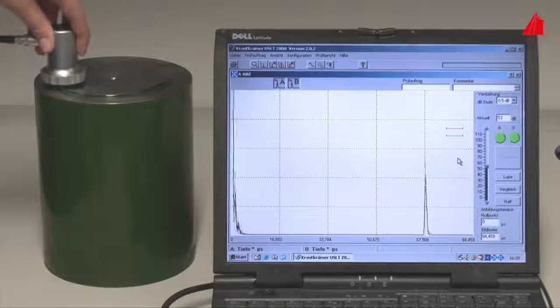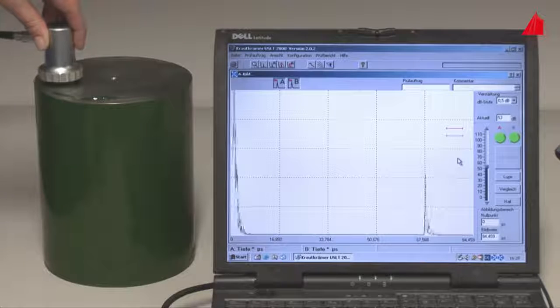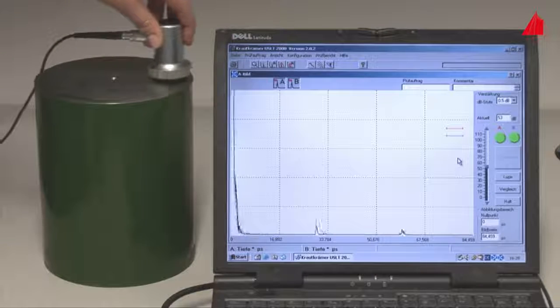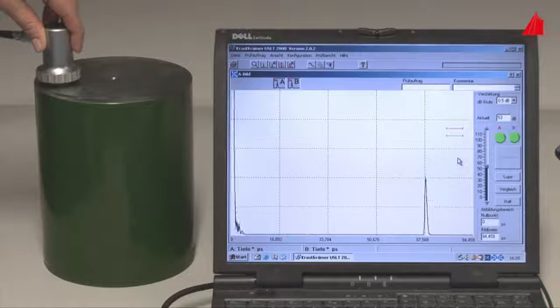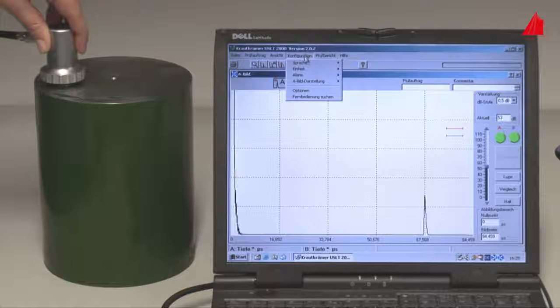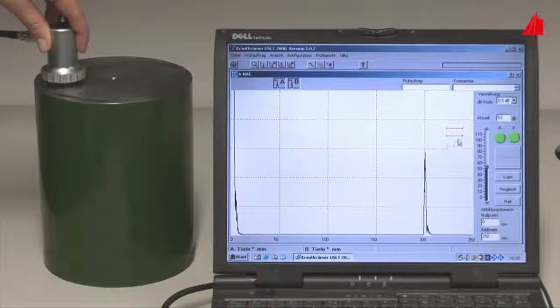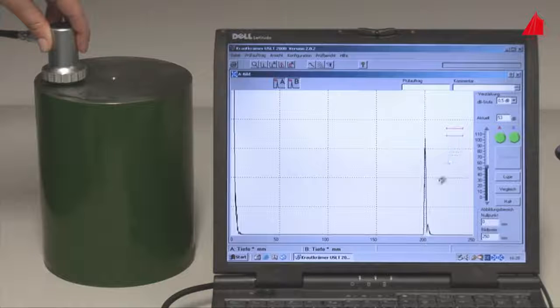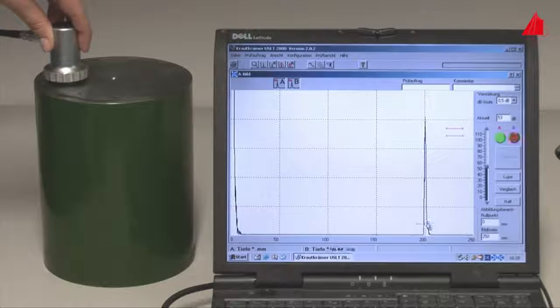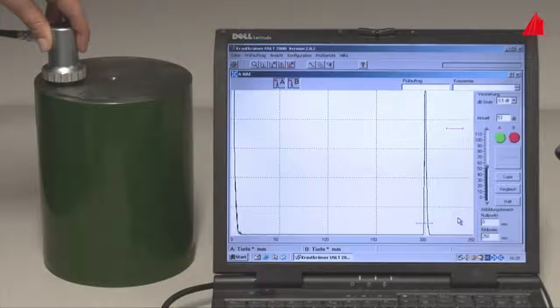The material tester spreads out the gel evenly on the top surface. That way she is able to examine the entire cylinder. Using the velocity of sound in the material, one can plot the calculated depth on the monitor to the right instead of time. With the help of so-called trigger gates, which may be set on the echoes with a computer mouse, the depth of the defects can easily be read off.